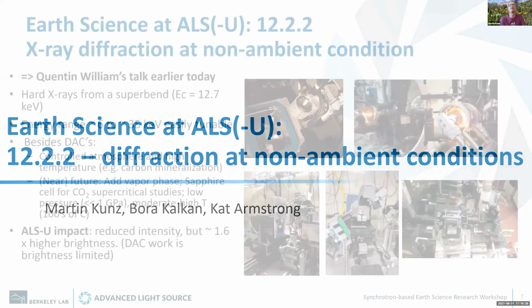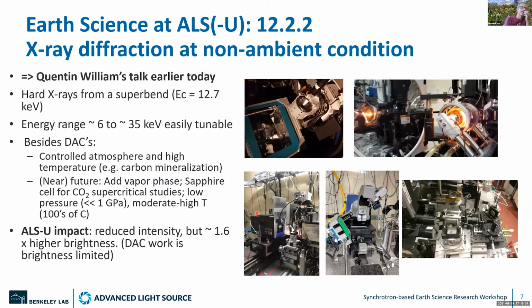12.2.2 is one of the beamlines that benefits from the superbend program. It has an energy range between 6 and about 35 keV. One thing which is really appreciated by our users is that we can easily tune the energy. We let users change their energy, which is, for example, used by people who do radial diffraction when they need to find their sample in a gasket that has low absorption contrast to their sample. Besides a strong demand from the diamond anvil cell community, we also have a strong demand from the general community who seek to do X-ray diffraction under non-ambient conditions with any kind of ancillary equipment.